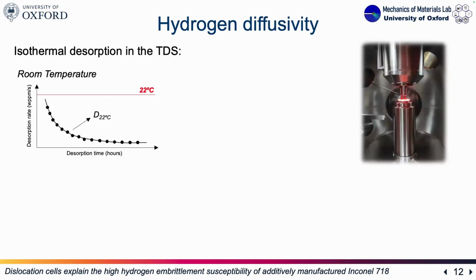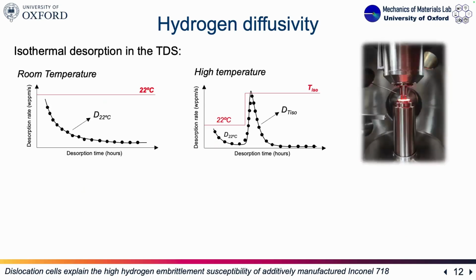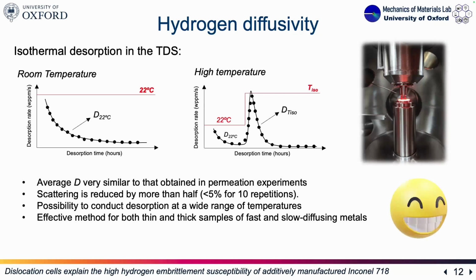Then regarding the hydrogen diffusivity, we have applied a technique that we have established in our group that works really well for both very slow and fast diffusion metals, and actually provides similar values to gas permeation. But it's very helpful because you reduce considerably the scattering of the measurement, and you can measure the hydrogen diffusivity at a wide range of temperatures.